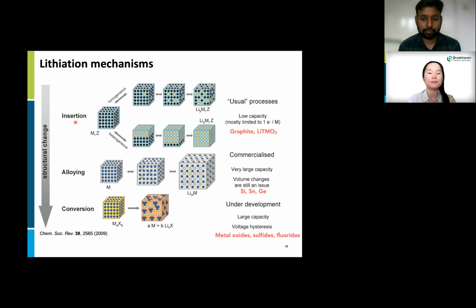ions are participating. Some materials can store lithium through alloying, and the alloying reaction requires multiple lithium ions, so it gives us much higher capacity. However, this mechanism gives us another headache, like contact loss or polarization because of the huge volume expansion.